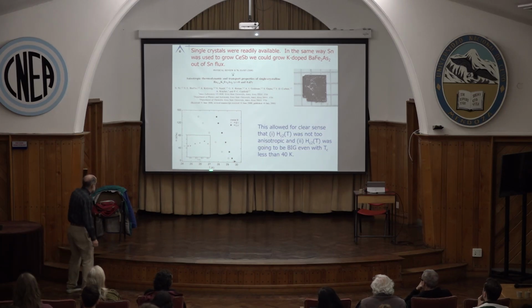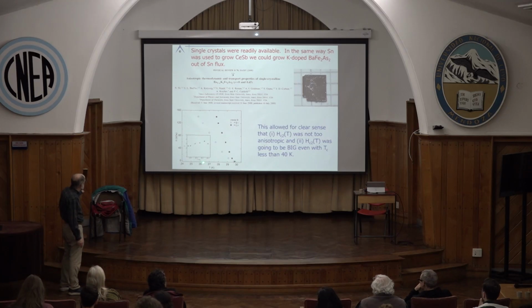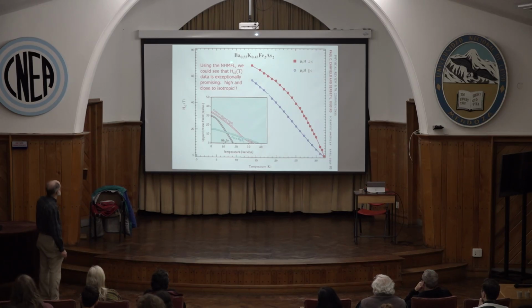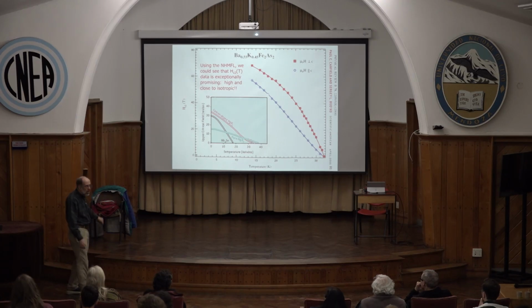This is field, this is temperature, this is HC2, and this is 14 Tesla. That's not a small field. By 14 Tesla, we've suppressed this by only about 4 degrees. That means we're going to have a big HC2. We went to the National High Magnetic Field Lab. We took it up to 60 Tesla. The anisotropy is clear, but it's relatively small, okay?